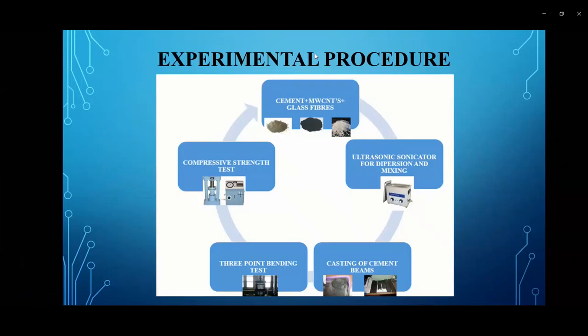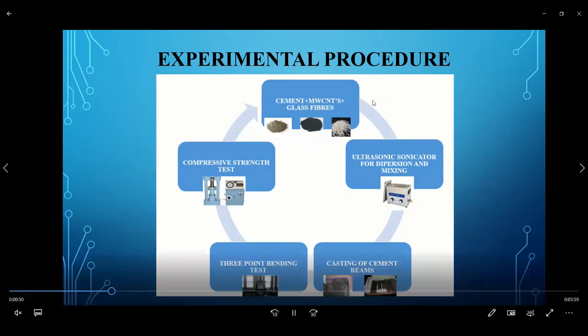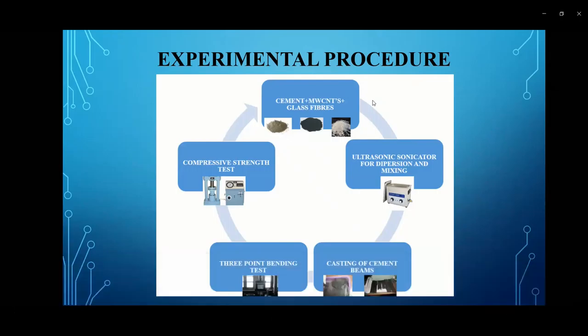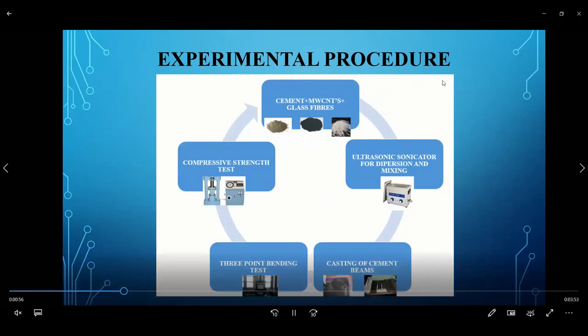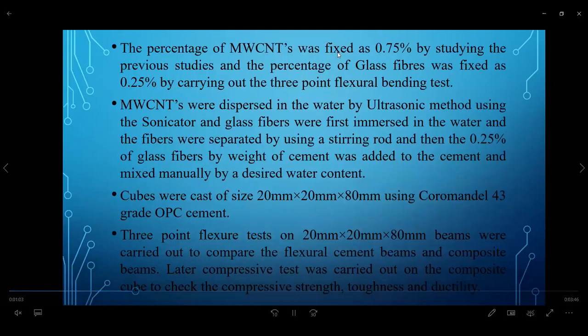This is the flow chart showing the experimental procedure, wherein we are mixing the cement with MWCNTs and glass fibers. Then the mixing procedure is carried out by an ultrasonic sonicator for dispersion and mixing. Then we cast the beams and cure them in water. Then we carry out the three-point bending test and the compressive strength test using a compression testing machine. The percentage of MWCNTs was fixed as 0.75% from previous studies, and the percentage of glass fibers was fixed as 0.25% by carrying out the three-point flexural bending test.